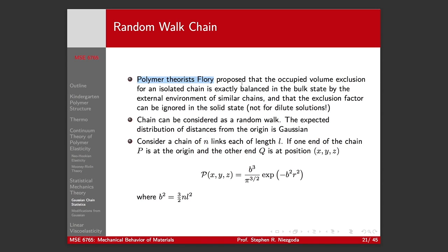And his real genius, I think, was describing the free volume theory for polymers, which is how I tend to imagine all polymer problems: the amount of free volume in the polymer system. But he proposed that the occupied volume exclusion for an isolated chain is exactly balanced in the bulk state by the external environment in similar chains, and that this exclusion factor can be ignored in the solid state, right? So not for dilute solutions.